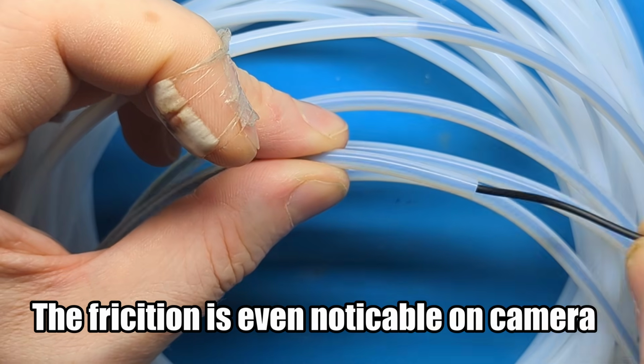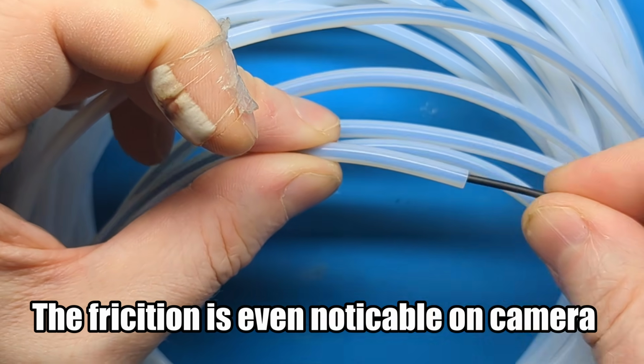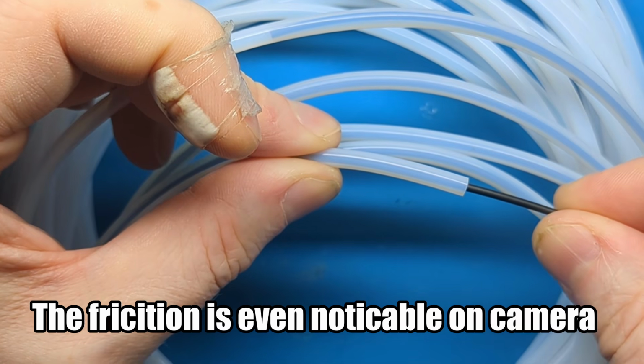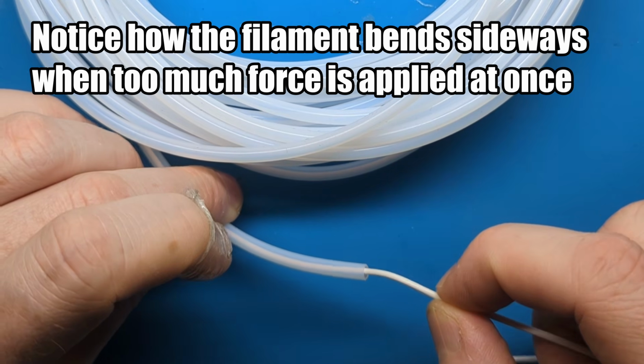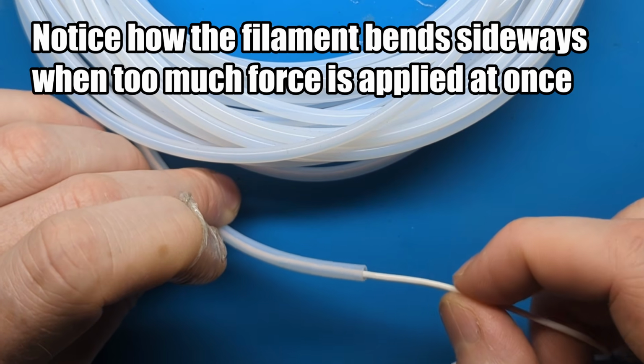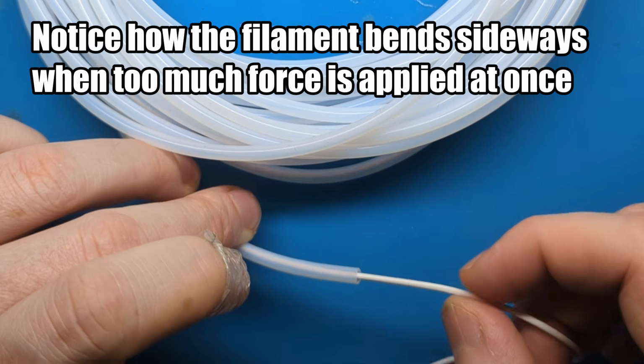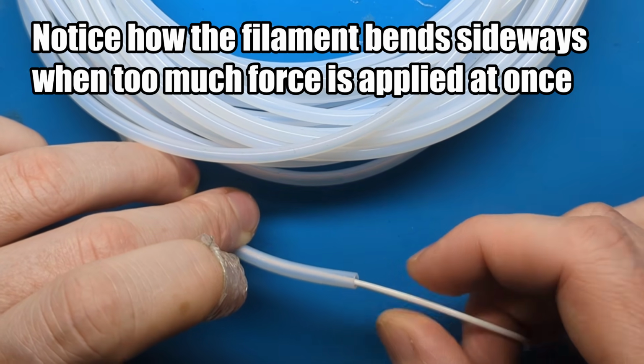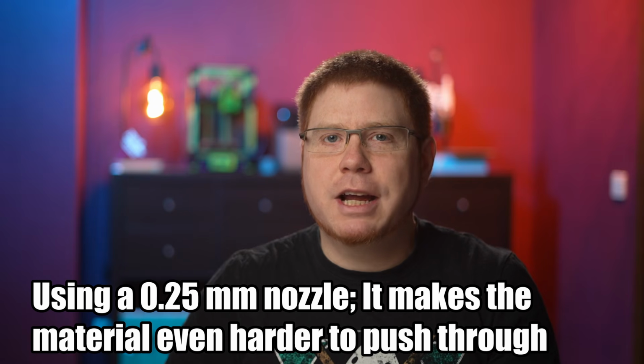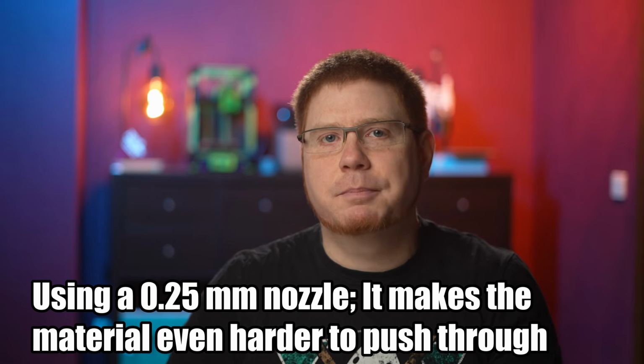With TPU, when retracting too fast, you might squish the string of material coming from the spool, often channeled through a PTFE tube, too much, which can lead to skipped steps on the extruder motor. The faster a stepper motor moves, the less torque it has overall. This is a bit hypothetical though. The retraction itself isn't usually the biggest problem. The real problems stem from building up the pressure again. In order to not get jammed, the filament needs to be pushed back into the hot end slowly. If retraction happens in rapid succession, even going slow might not prevent the tool head from getting jammed. On my Voron 0.2, for example, I couldn't get retraction to work reliably and I ended up deactivating it altogether. This isn't an insurmountable obstacle though.